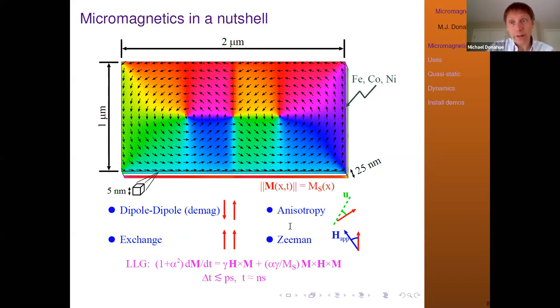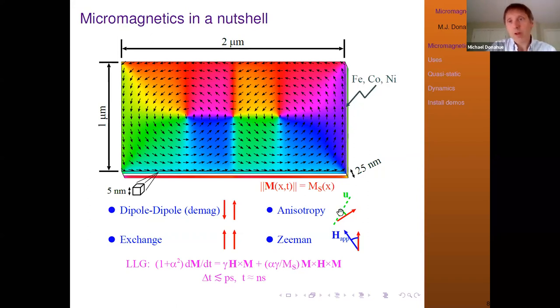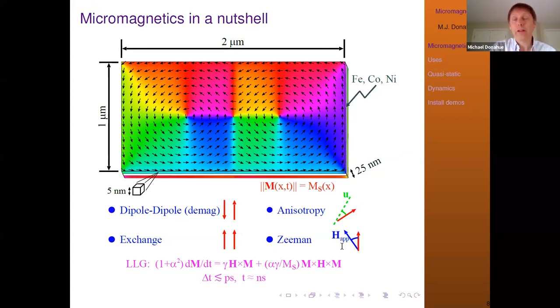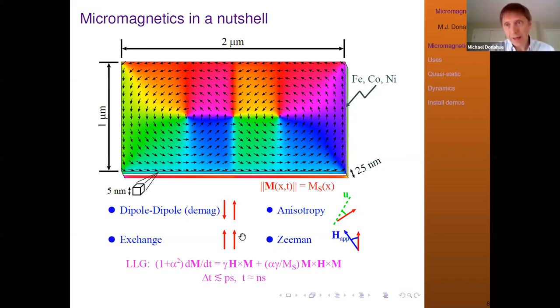The contributing energy terms include: the exchange interaction, a quantum-scale interaction between neighboring atoms where spins want to line up, which is the origin of ferromagnetism and domains; the dipole-dipole or demagnetization (d-mag) field, which tends to break up domains — this is why the entire piece isn't one single domain; anisotropy, due to local crystal structure giving preferred directions for the magnetization; and the applied field, which causes magnetization to rotate into its direction. Additional terms like temperature fields can be added as OOMMF extensions.